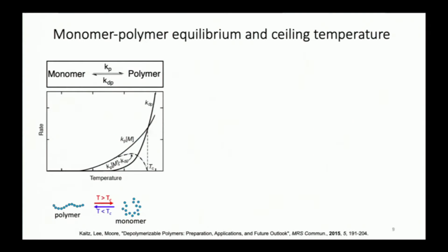Let's see what happens if we reduce the problem in the simplest way possible. It's long been known that there are certain monomers that are able to be polymerized, but that monomer-polymer equilibrium is carefully balanced, and so you can find a temperature and, for example, a monomer concentration, as this plot shows, where the rate of polymerization is equal to the rate of depolymerization. So the rate of polymerization is that curve, and depolymerization is this curve, as it's plotted as a function of temperature. Where those two curves meet, there's a rapid exchange between polymer going to monomer and monomer going back to polymer, in equilibrium under the conditions usually of the polymerization.